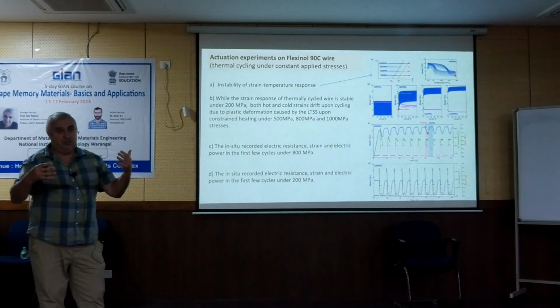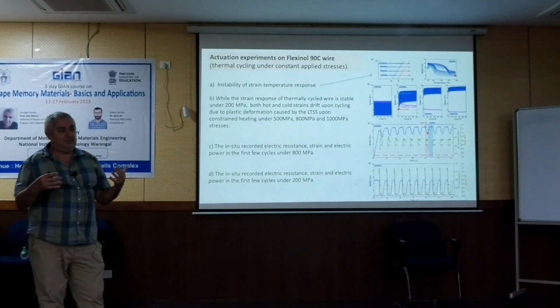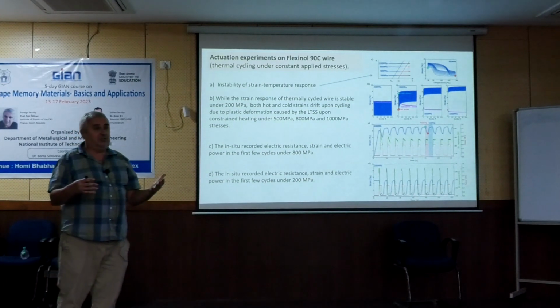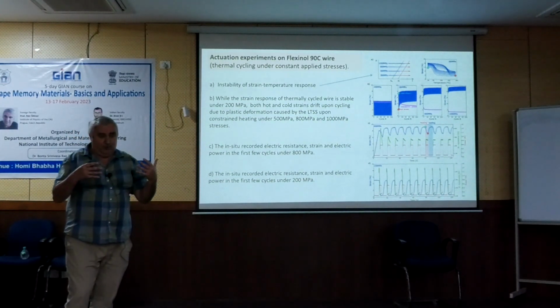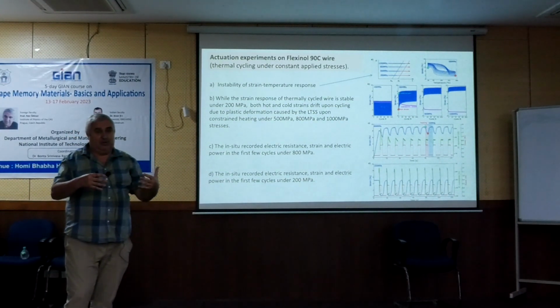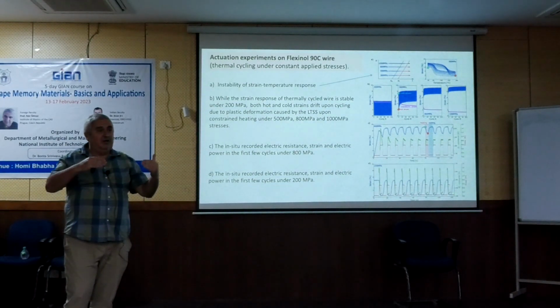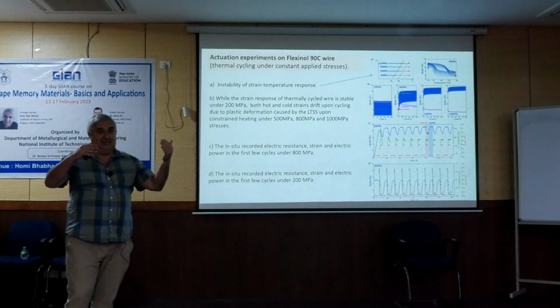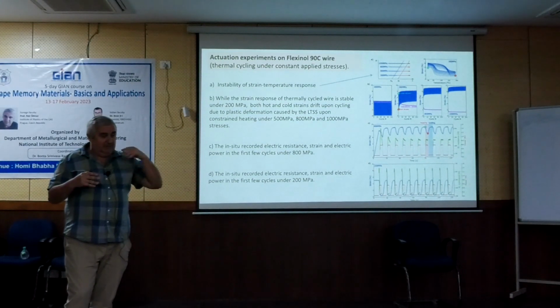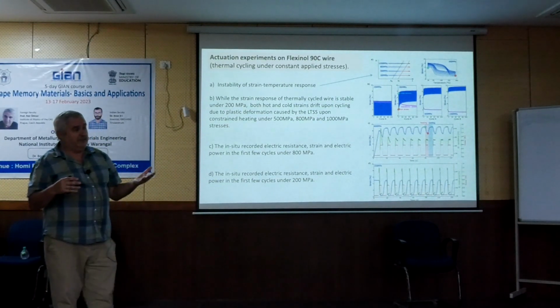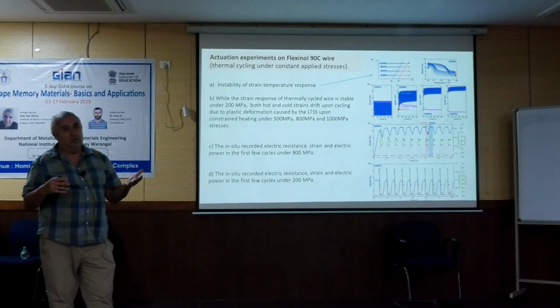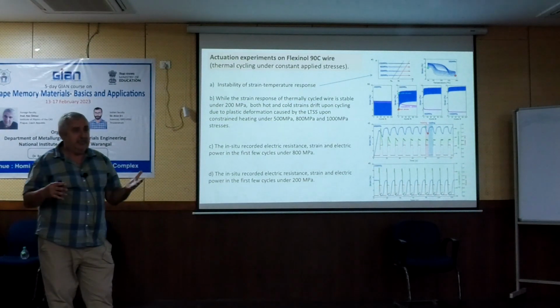High temperature shape memory alloys are always resistant against dislocation slip. If you suppress the dislocation slip, you can go up to 200, 300 Celsius. The most successful high temperature shape memory alloy now is nickel titanium hafnium, but it is a very brittle alloy, so there are a lot of problems with it, but it already works.